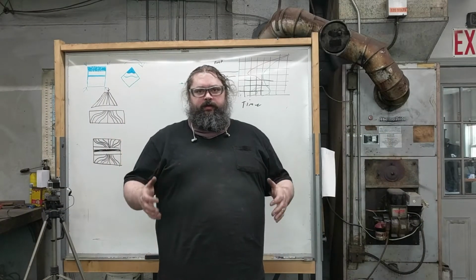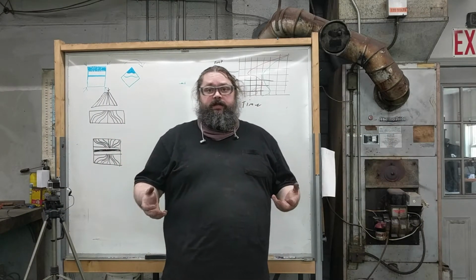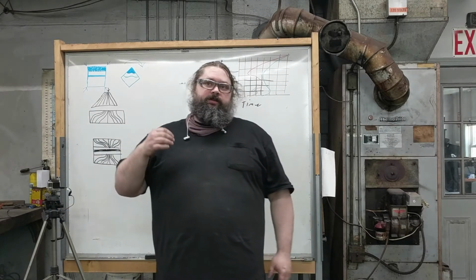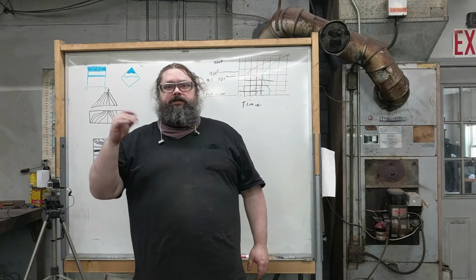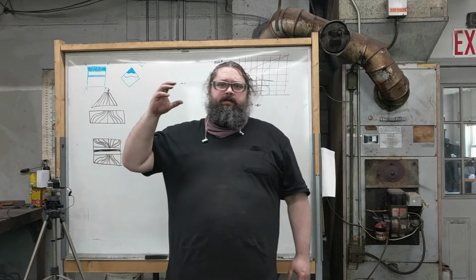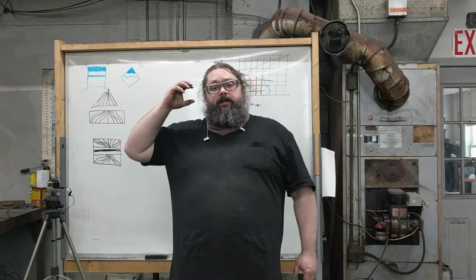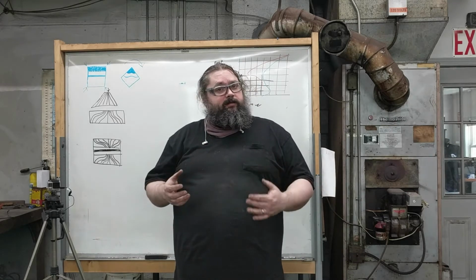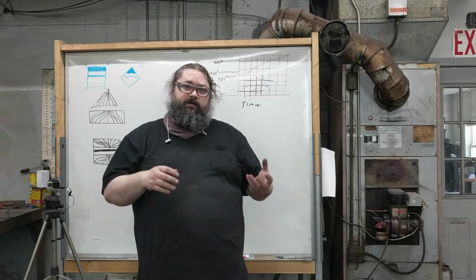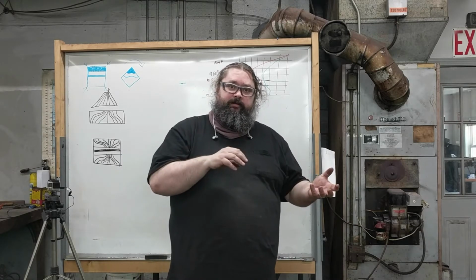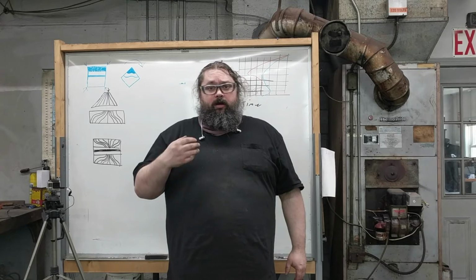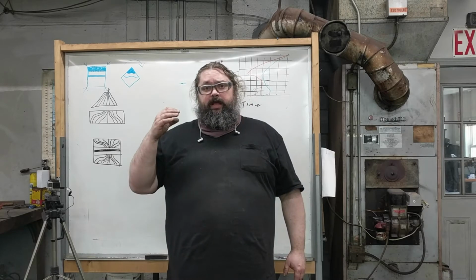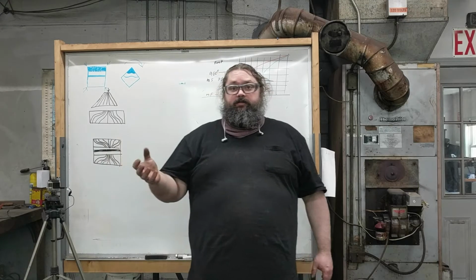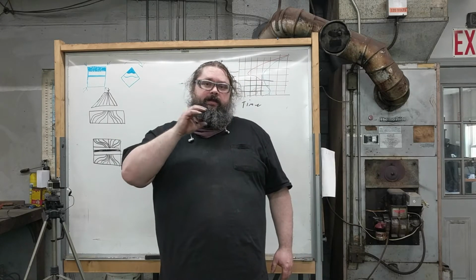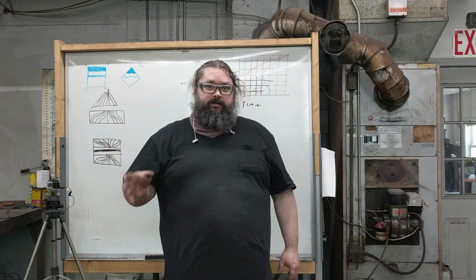There we go. Okay, so I figured I'd take a minute and explain why cryo is necessary for stainless. So in most carbon steels, you end up with a little bit of what's called retained austenite every time you quench. And that is the high temperature structure of steel that exists at room temperature, but it doesn't really want to exist at room temperature, so through either tempering, dislocation, it can kind of convert back to martensite. In carbon steel, it's usually not too much of an issue unless you really have a very high carbon content and screwed the heat treat up. As long as you're careful about it, you don't need to cryo carbon steels.